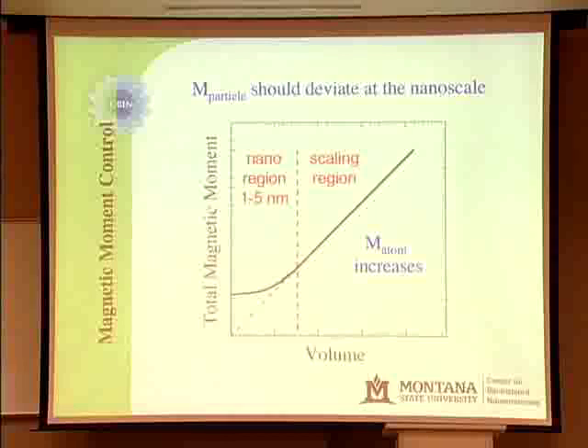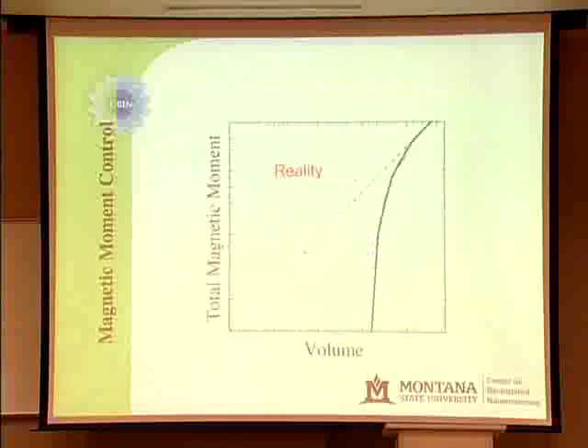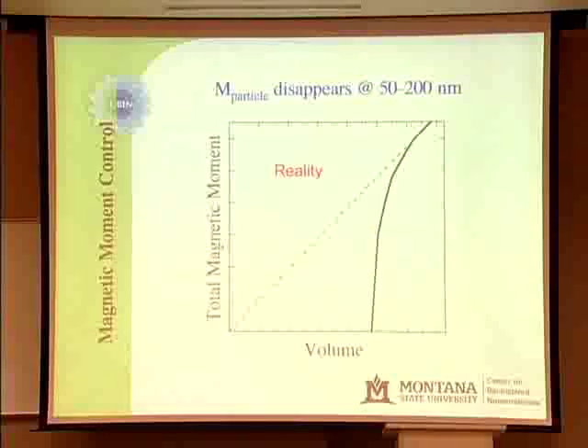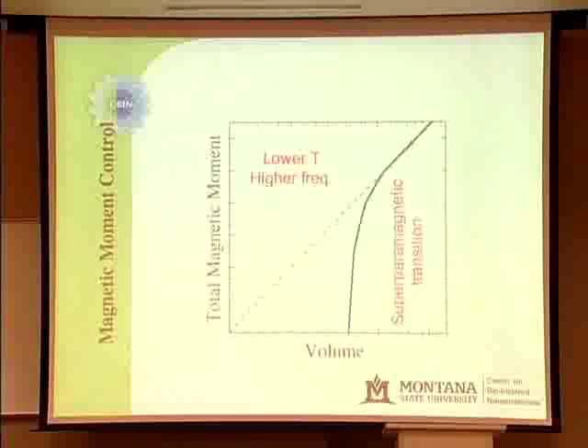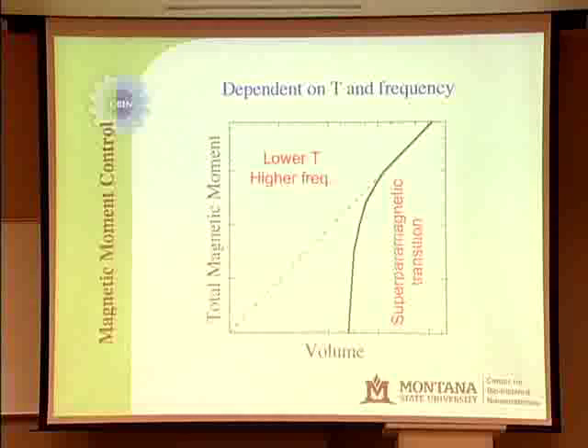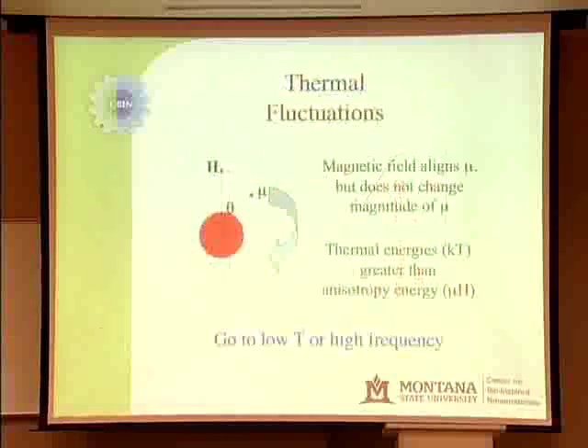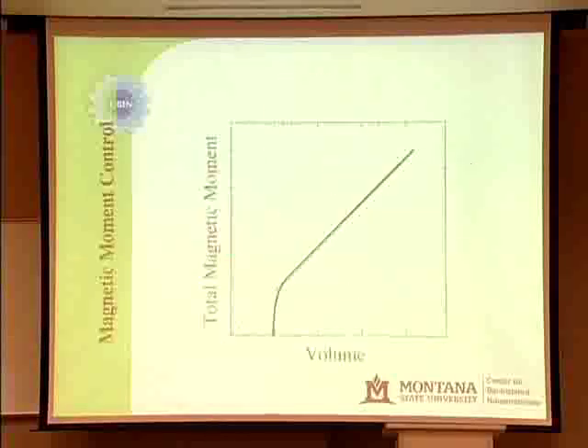So we did it. First thing we did was we grew some particles, and in reality, the moment disappears right away. This is the particle problem I talked about before. It's something called the superparamagnetic transition. It's understood by scientists. We know how to get around it by going to high fields, low temperatures, higher frequencies, and that gets rid of this after effect. We did that. I'm not going to go over what superparamagnetism is, but we did that, and it still decreased.